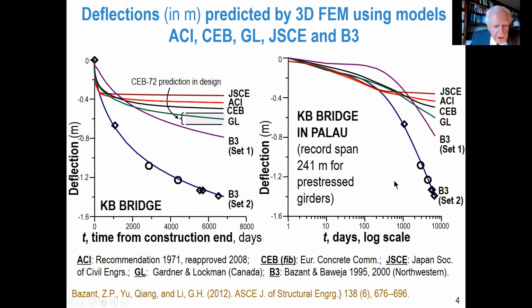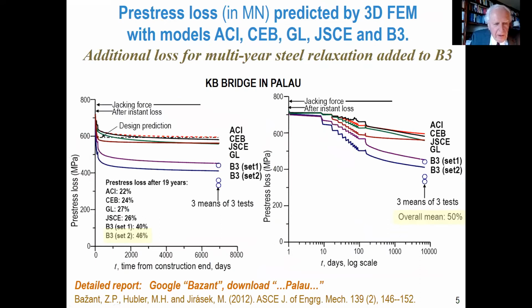It was analyzed in detail, and we also, of course, had to analyze pre-stress loss, which was very interesting since it was found that it was not like in design, where we assume about 20 to 25%, which is tolerable, but it exceeded 50%. These are measured pre-stress values when they bared the tendons and measured the retraction, and these values are far more than assumed in the codes. On the other hand, with the B3 model recalibrated on that concrete, it was reasonably predicted.